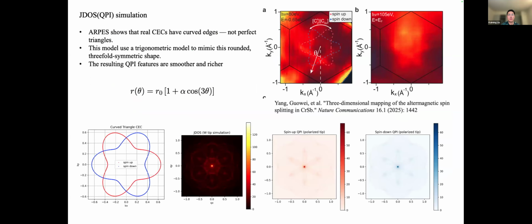After I went back to UIUC, I did some simulations. I used this model to simulate the quasi-particle interference for chromium antimonide. From the ARPES data in this paper, we know the real constant energy contours in chromium antimonide are not perfect triangles. They have rounded curved edges. So here we used a simple trig function to mimic that shape, which is still threefold symmetric but smoother. As you can see, the resulting joint density of states and the spin polarized QPI look more realistic, and the features are richer, and the overall pattern is closer to what ARPES and STM might actually show.